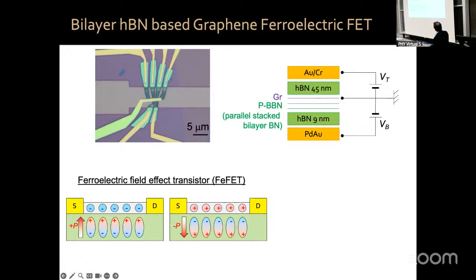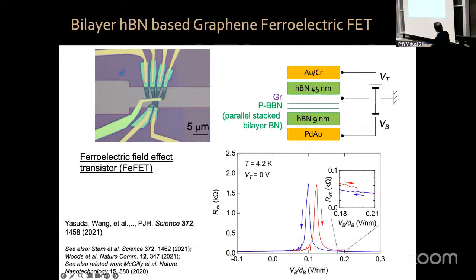That gives rise to this resistance versus voltage curve, where if you measure in one direction, you have this peak in resistance. Remember, graphene's conductivity is V-shaped, so resistance, which is 1 over conductivity, is a peak versus density. So you measure this thing. At some point, the ferroelectric switches, then you go back and measure this hysteresis. This was measured not only by us, but by several other groups at the same time.